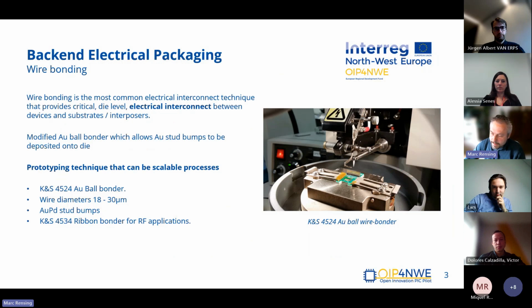We already have well-established and developed electrical packaging capabilities, and these are also available through the pilot line. And a number of wire bonders are used for making electrical connections between devices and substrates. So two of the most popular wire bonders we would have would be a gold ball wire bonder with wire diameters ranging from 18 to 30 microns. And this particular tool has been modified to allow us to apply gold stud bumps onto individual die. And these can be used then in conjunction with solder ball jetting and flip chip bonding for electrical packaging prototype development. And then we also have a ribbon bonder for RF packaging applications.